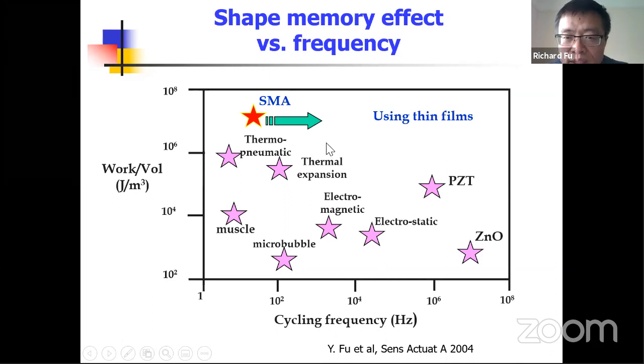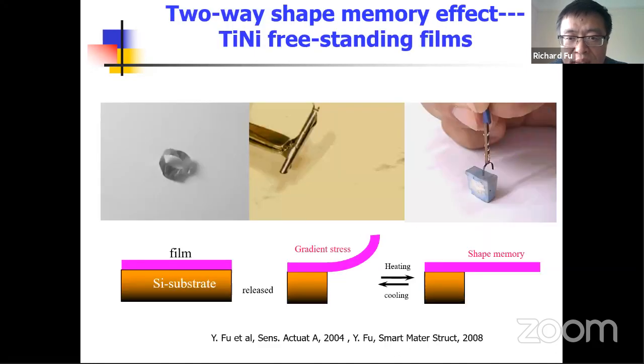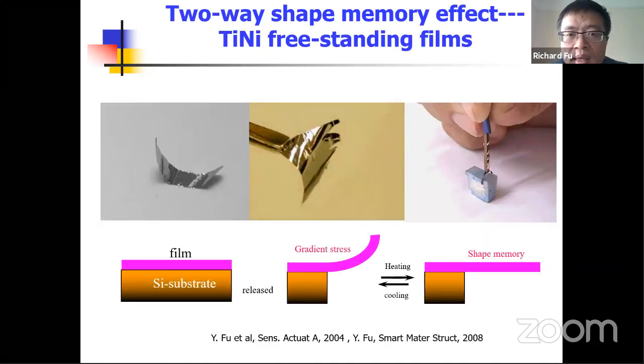One way to realize it is to use the thin film structure. We only have a few microns, which is easy to heat up and cool down. And also we can use the MEMS design. We use microdevices and make it at a much smaller scale. So that means heating and cooling is much faster. So it's a scaling effect.